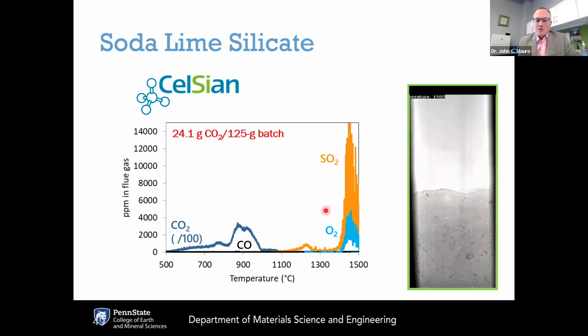Then at these higher temperatures, there's sodium sulfate that's included. That is what's called a fining agent that actually releases more bubbles to increase the size of the bubbles so they rise to the top faster and you can get rid of them faster.